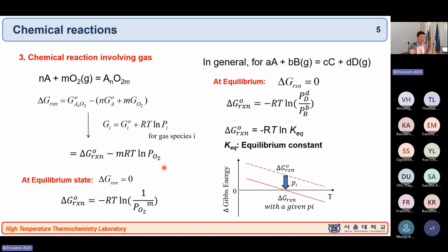At a given temperature, if I want to know exactly the transition from iron and oxygen becoming iron oxide, that oxidation condition or reduction condition, we can just set this equation, delta G of reaction, equal to 0, and that gives you the answer for how much partial pressure of oxygen I need to maintain that condition. That's typically what we call the oxygen partial pressure on that borderline. And when you consider more and more other gas species, we can just generalize this equation like this.